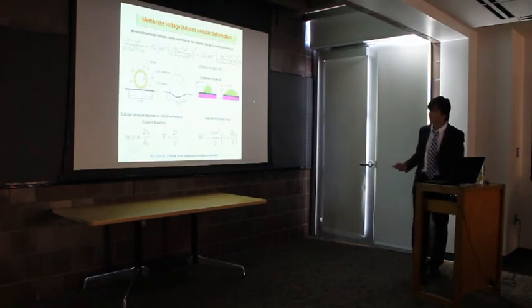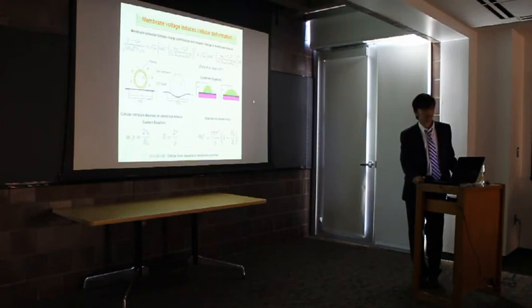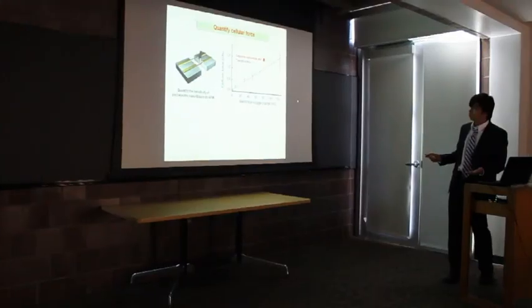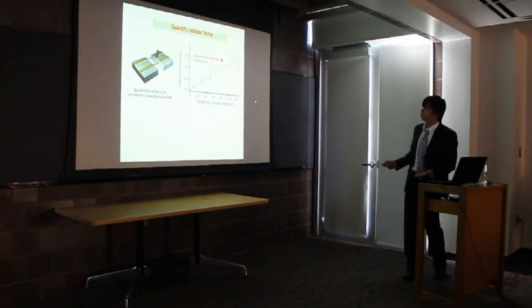In this experiment, we have the pipette tip on top of the cell. Now we can confine upward deformations, and most of the force is applied underneath the cell, on the very thin, super thin piezoelectric ribbons. But when you apply the current, and you've got a very hard boundary up top and a pretty stiff boundary on the bottom. We do the calibration on the cellular force that the cell applies onto the PZT ribbons upon different membrane voltage depolarization.